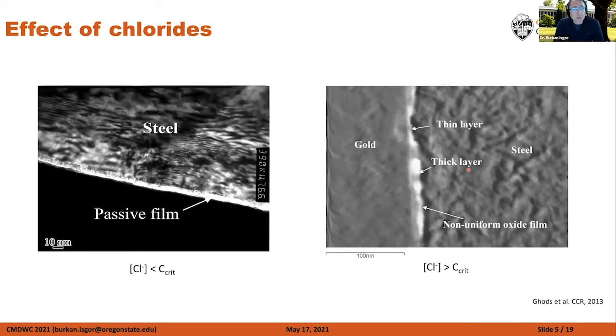Now, our topic today is more about what happens to that passive film when you add chlorides. We always talk about this critical chloride threshold concept, and theoretically, there is actually a reality to that. If you, for example, add chloride into that pore solution where you passivated those systems and you keep the chloride concentration low, you actually don't see damage on the passive film. But when you exceed a critical chloride content, you start seeing damage on the passive film. So there is an actual concept of critical chloride threshold. There is a big debate about how practical that is or whether it is useful or not. But from theoretical discussions, we can say that there is actually a critical chloride threshold.